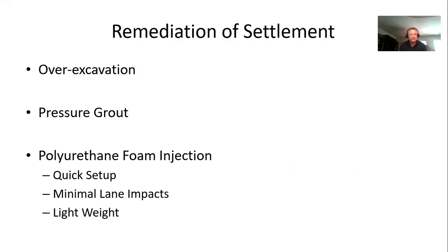Again, looking at this, then we could consider over excavation, pressure grouting, polyurethane foam injection. I touched on over-ex. Pressure grouting with cement. The only reason I tend to lean away from this on embankment fills is that you're adding a lot of weight to an embankment when you use cement. Unless you get your pressure bulbs stacked on one another, you're going to have gaps in between where the weight of that grout is going to tend to want to collapse on the next bulb. And so if you have a bunch of independent bulbs within the fill, with any one particular hole, these bulbs, which are heavy, are going to want to consolidate onto one another. And so I've always tried to avoid that by going with something lighter.